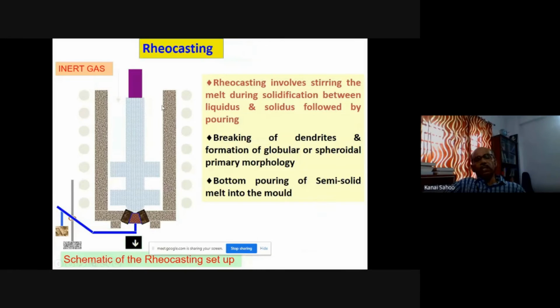Okay, so semi-solid processing, semi-solid casting may be thixoforming or rheocasting. In thixoforming, you have to prepare the feedstock material, then heat it inductively or in a furnace, make it semi-solid and put it in a sleeve or high pressure die casting, so that you can make the required shape of the casting and the desired product. And rheocasting, this facility we have in our lab. So rheocasting involves stirring the melt between the solidus and liquidus, because the mushy zone is there, so that all the dendrites formed are broken into smaller pieces during solidification, and take the globular shape of the casting.